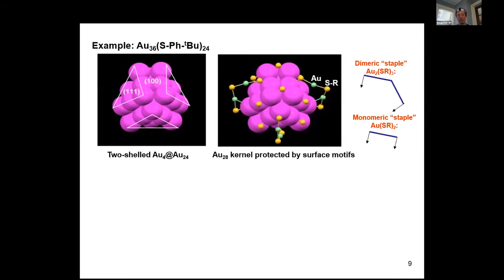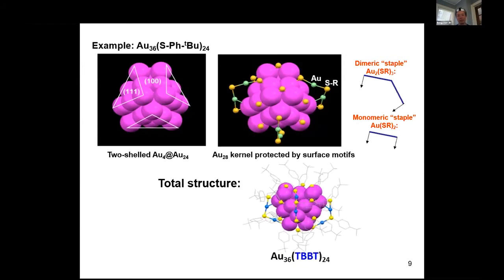If you have 2 gold atoms, we call it a dimeric staple. And if you have 1, we call it a monomer staple. This is kind of jargon. And then ultimately, the total structure. So you can also map out the carbon tails. And so this is a gold 36, which is relatively small.